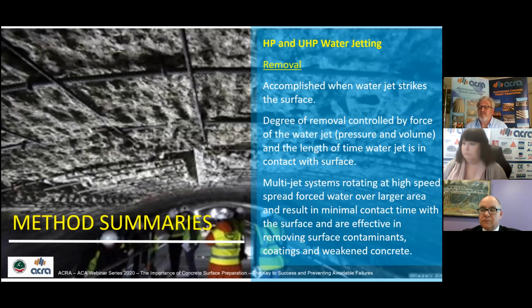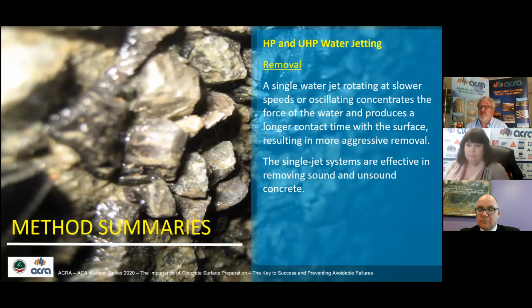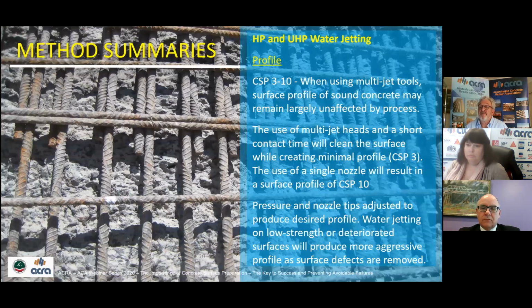Multi-jet systems rotating at high speed, 1,000 to 3,000 RPM, spread the force of the water over a large area, resulting in minimal contact time with the surface. Multi-jet systems are effective in removing contaminants and weakened concrete. Single water jet systems, rotating at slower speeds, 300 to 900 RPM, or oscillating, concentrate the force of water and produce a longer contact time with the surface, which results in more aggressive removal. Single jet systems are effective in removing sound and unsound concrete.